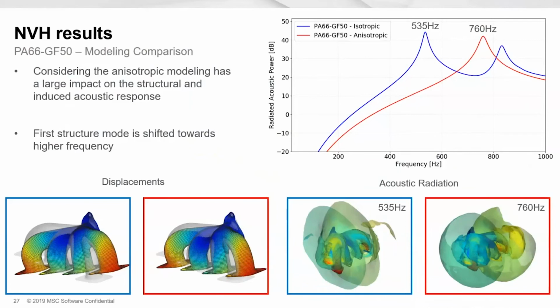Here what we are looking at is a first comparison between the classical approach, where we use isotropic material information, versus a first anisotropic study for the same fiber density of 50%. And what we clearly see on this first response is the strong impact of considering anisotropic material properties on the acoustic radiation power that we look at.